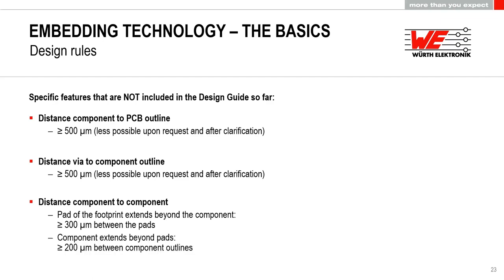The first point basically is we look on the footprint, and if the footprint extends the outline of the component, then we look on the distance between the pads, and this should be, in our favorite way, 300 microns, so that we get, for example, in the solder technology, still a solder bridge between the pads, or when we look on the glue technology, that the glue fillet is not touching the glue fillet of the other component. This might get to assembly issues if the glue dots and the printed glue flow together, and therefore we need to have at least 300 microns.